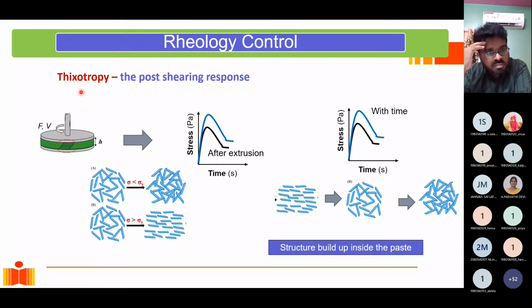Thixotropy is another property where, once I induce flow, so I've sheared the material, initially the material has densified, then with application of shear, the network ruptures and I get all these aligned particles. So the material is flowing. But after I remove the shear stress, suppose I put it at rest. So now this is simulating the condition where I've sheared the material, I pumped the material. And when you're pumping the material, the fluid is under a lot of shear stress. I pumped it, I've sheared it, and then I put it at rest. That means I've now brought it to rest.